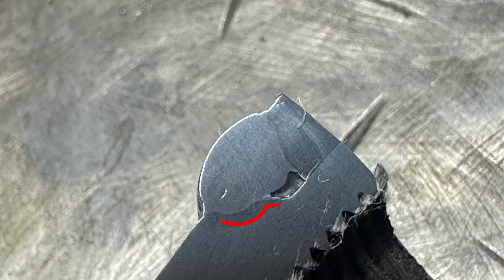Now in this picture where the red line is, I put that there because you can't really see it in this picture, but I'm 99% sure that the lack of fusion actually goes up that whole side there, or it's a crack, because I ground that down multiple times and almost the whole length of it has like a raised edge that I couldn't get rid of even when I ground down through it quite a bit. So either the bead cracked off of that, it's a lack of fusion, or who knows, maybe could just be anything, but it's highly suspect. Even though it looks like it fused in there, it's just suspect, so not good at all.